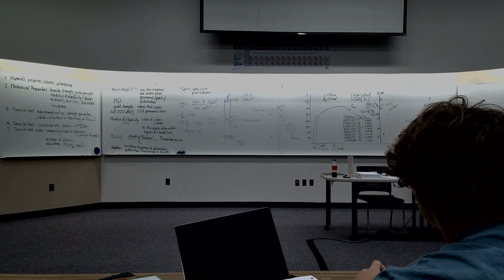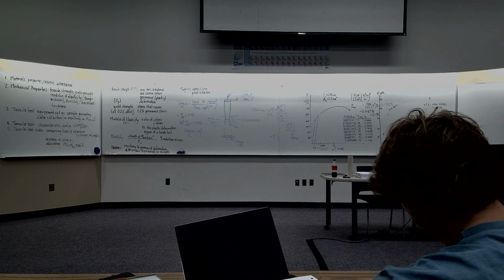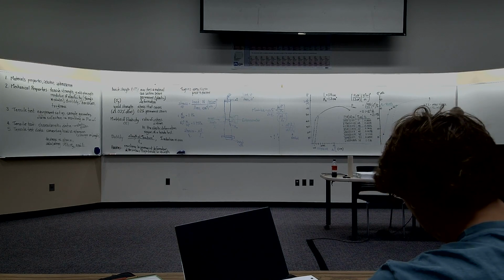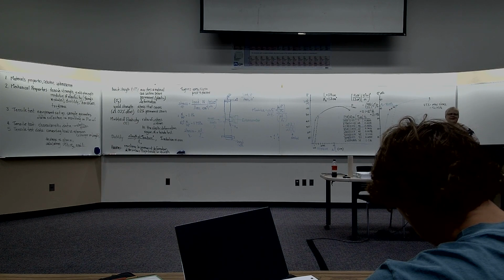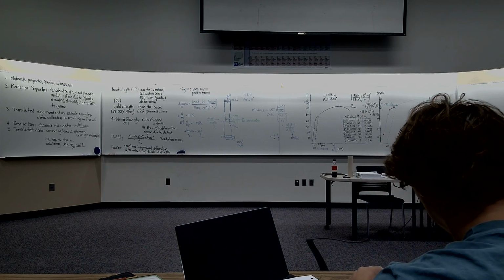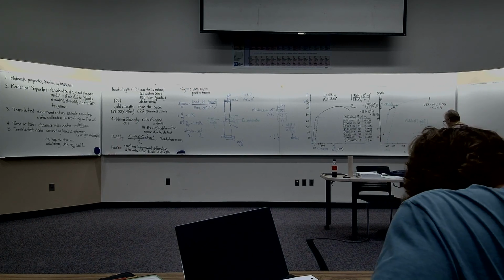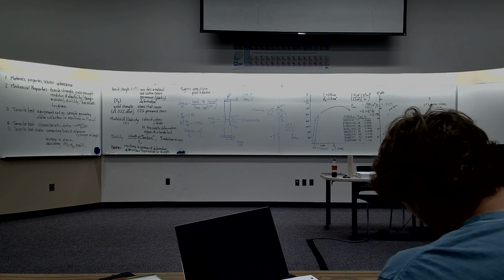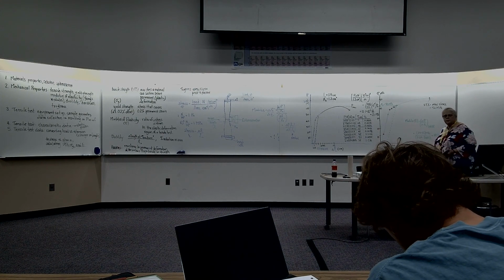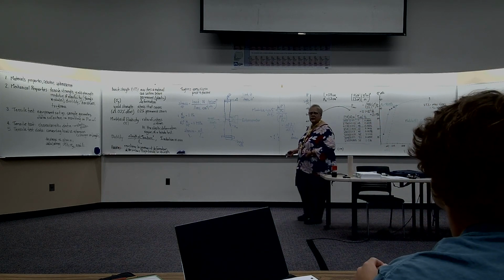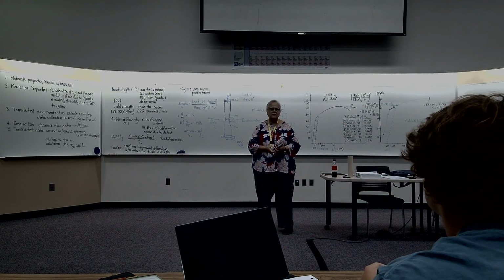So I'm getting 1833 megapascals. The modulus is usually given in gigapascals, which is 10 to the 9. So that would be 1.83 gigapascals. Modulus is typically around 1,000, on the order of 1,000 times bigger magnitude than the stress.